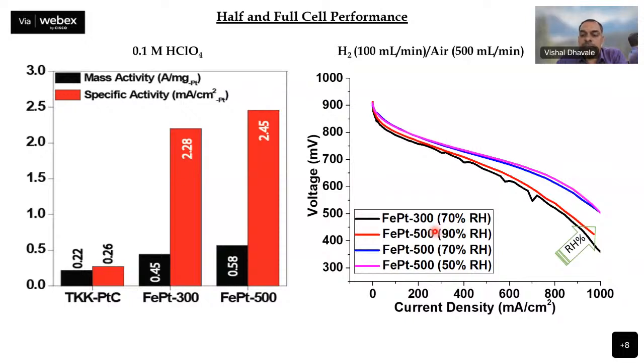Along with that, with the same nanocapsules of 500 size, at different RH conditions of 90, 70, and 50, you can see the decrease in performance. So overall, you can see that this capsule can be used at low RH conditions also, and it gives a clear indication that as the capsule size increases, the vacant spaces between the interfacial capsules can be used for better management of the mass as well as the oxygen. So diffusion resistance can also be reduced, and the oxygen partial pressure is increased with this.